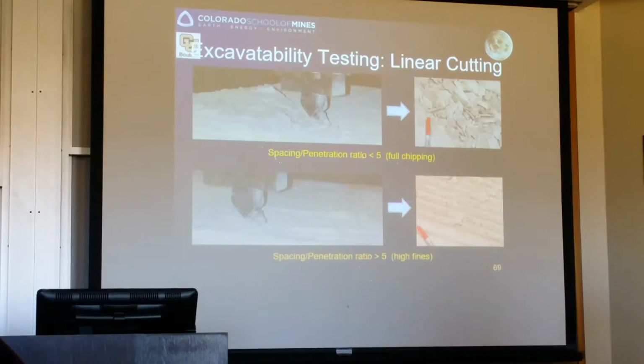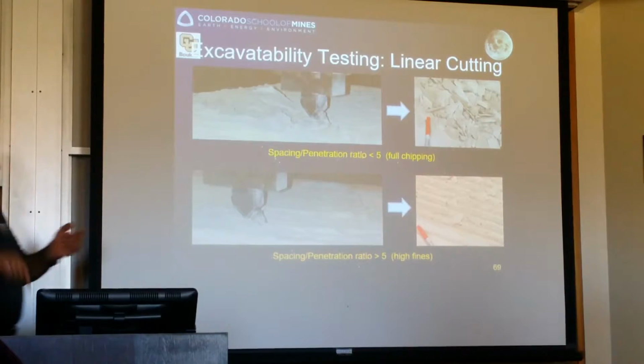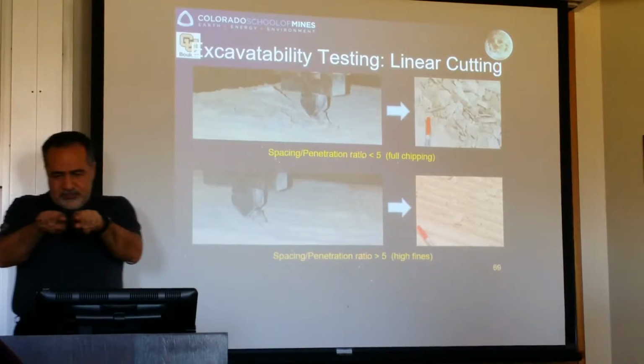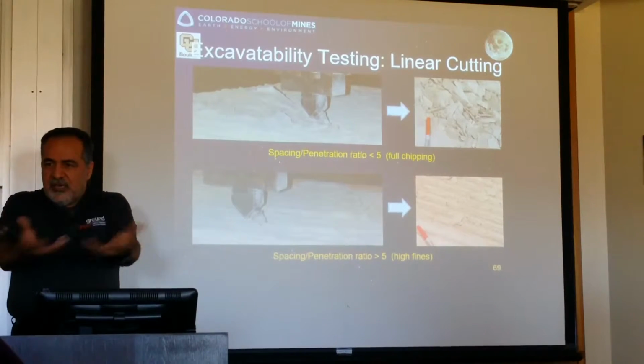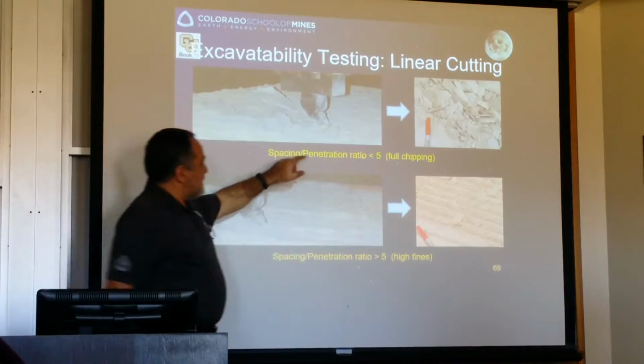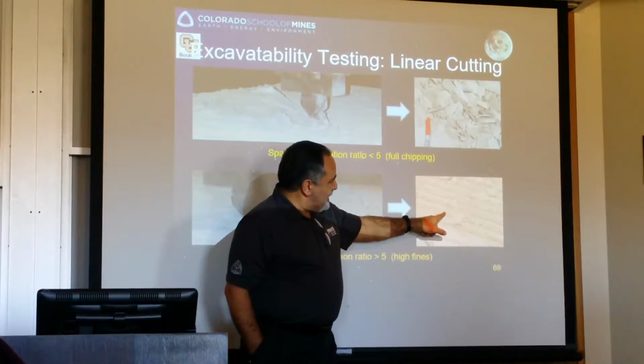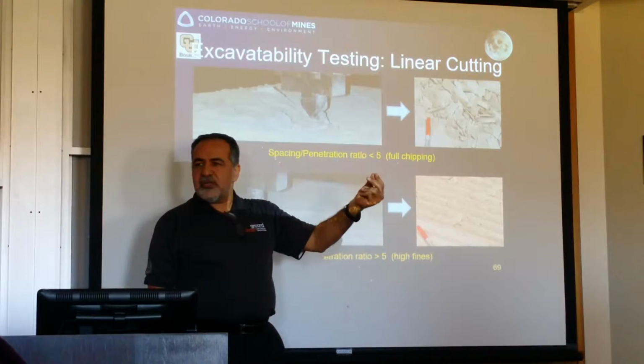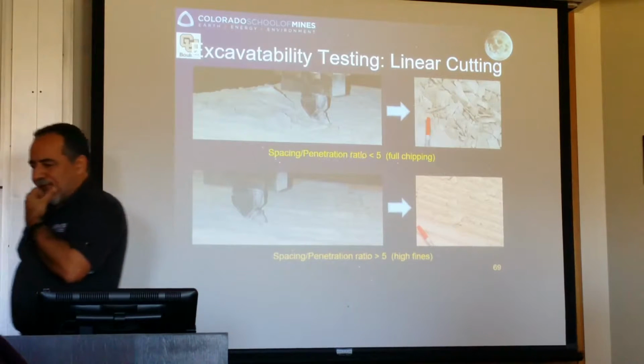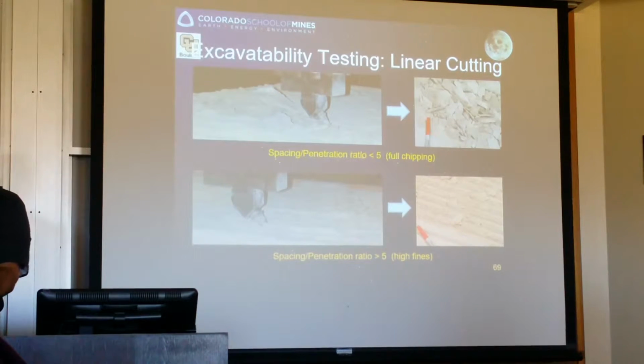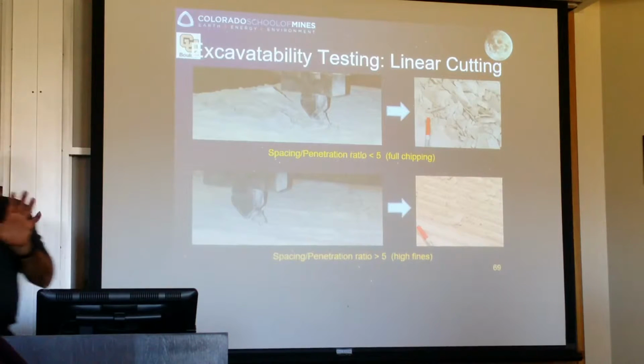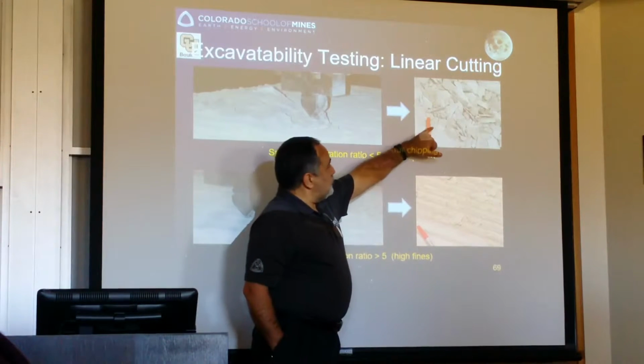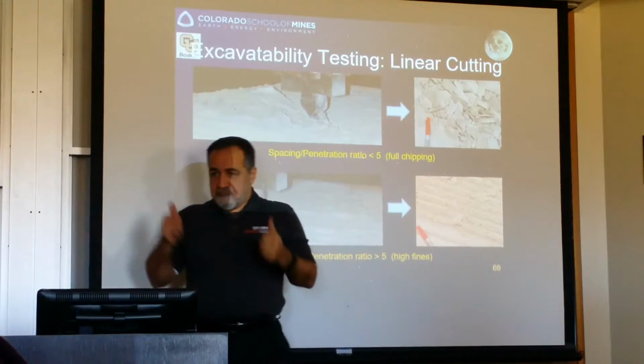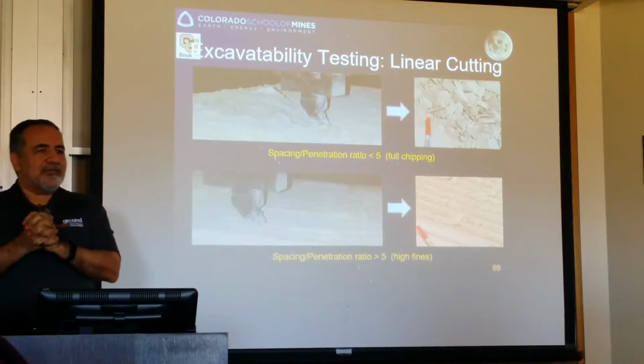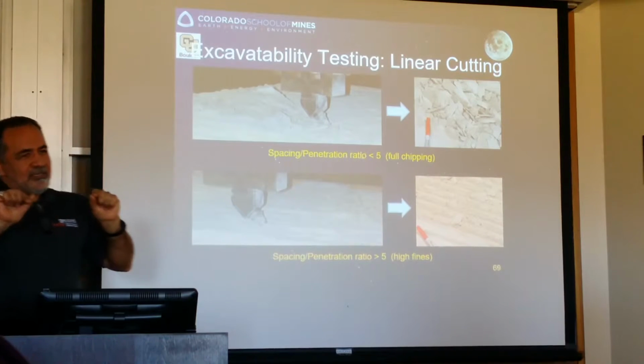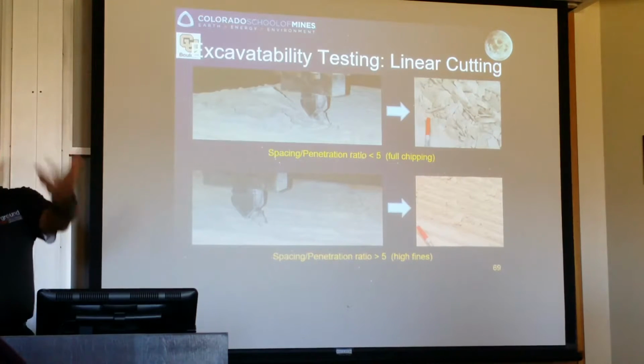We first did what we call linear cutting test, cut it in line with different spacing. So change the spacing between the cuts to see if we can actually cut the material. And you can see if the spacing is too small, you make a lot of fines. It takes a lot of energy. Energy deployment in that material means that it could actually evaporate the water. So it's not really wise. If the spacing is too large, if you get good chips, that's a good achievement. But, oh boy, you have to penetrate just enough to make the chips pop up.